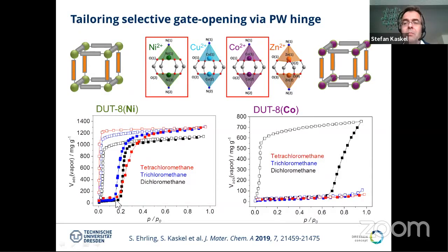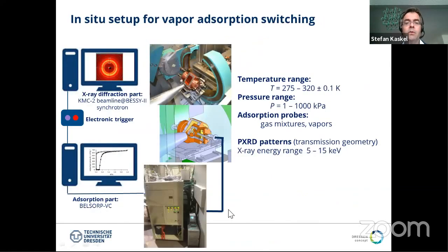And what is fascinating to me is that here we exactly see this selectivity behavior. So the DUT8 nickel, for example, when we look at the adsorption isotherms for chlorinated methane, dichloromethane, trichloromethane, tetrachloromethane, they all look more or less the same. It's just a bit boring, but it's completely different for the cobalt system. Trichloro and tetrachloromethane, they cannot open the pore, but the dichloromethane, it opens the pore, and we have a huge adsorption capacity. And this shows that we can tune the selectivity by tuning the energetics of the hinge. And this is one way, one initial understanding of how we can tune the properties of these types of materials.